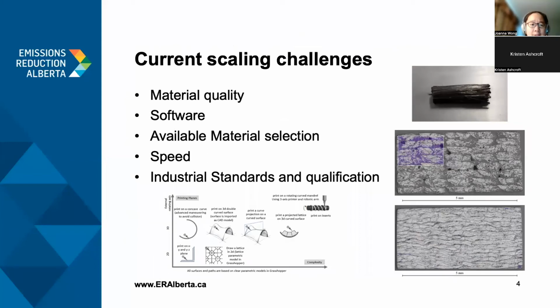Okay. So the current challenge in additive manufacturing is really in achieving the material quality that you would expect from an end-use component. If you look at the square in the middle, where you see a little purple highlighted region, this is a typical microscope image taken from an additive manufactured part using, say, a standard commercial process.